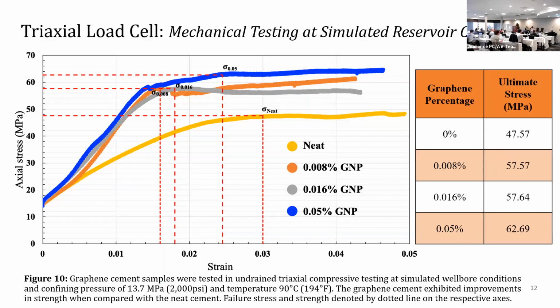In this one, it turns out that the 0.05 actually performed better than the 0.008. And so my take on this is that it is really important to apply different methodologies when you are validating a material and qualifying it for any application in the field, because this data is in slight disagreement with the nano indentation, which was not done in confinement.